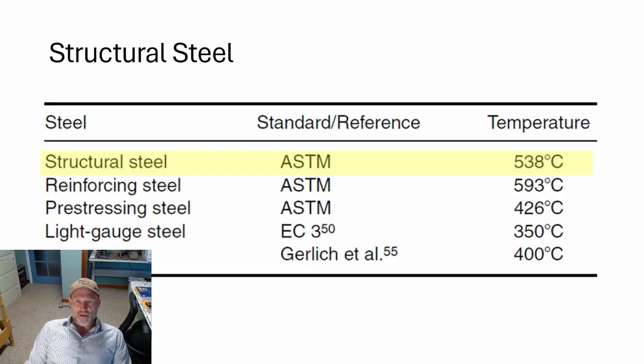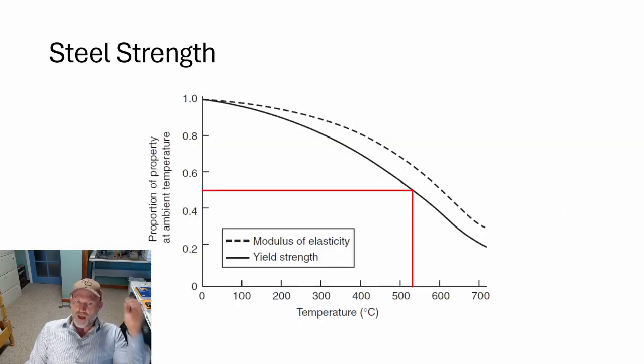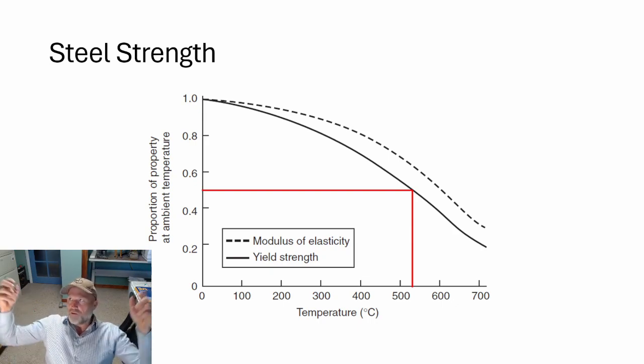So this is basically the threshold for design. It's 538 degrees Celsius for steel. If you look at why that is, this is from the SFPE Handbook of Fire Protection Engineering. What happens over time with steel is there are two factors: the yield strength, the actual strength of the steel, and then the elasticity of steel. So it's like a spring. If you exceed a certain amount of force on a spring, it's going to be deformed. So the modulus of elasticity gives you the amount of stress you can apply to that spring and still have it come back to its original form.